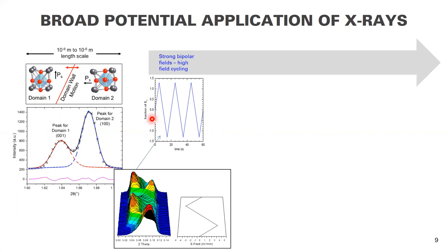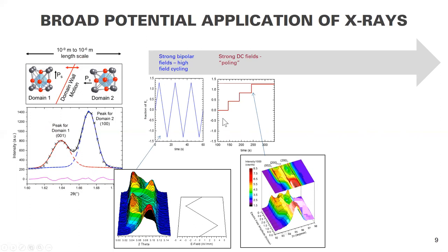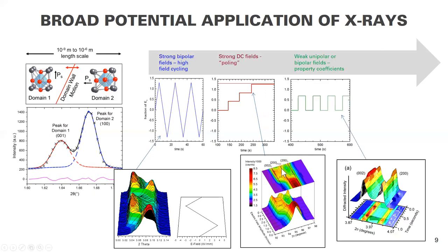And so you could think about applying very large bipolar, high field cycling, and tracking using X-ray diffraction how the peak intensities change. You could also think about applying strong DC fields like you'd see in electrical poling of piezo ceramics. And you can see significant changes in the relative intensities and the emergence of new reflections in these situations.